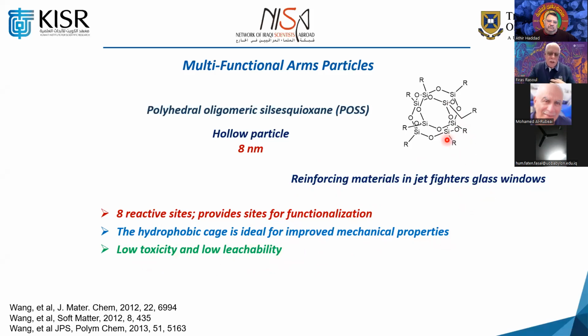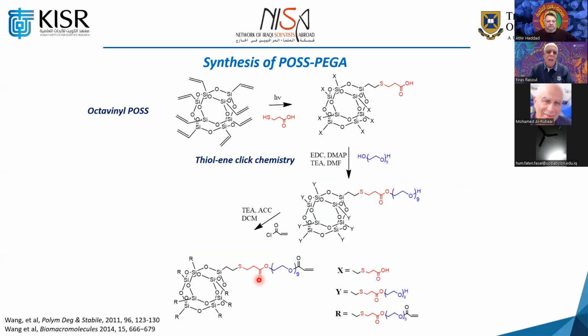But in our case, because we're not going to use it by itself, it's going to be attached to other polymers. So the leachability will definitely be diminished. What we did, we bought this type of functional group. It has a carbon-carbon double bond, which is octavinyl POSS. And we reacted it in a fantastic, very fast, very efficient reaction, the thiol-ene chemistry under UV light. It just goes like that. Probably less than 1 minute, the reaction is clean and completed.